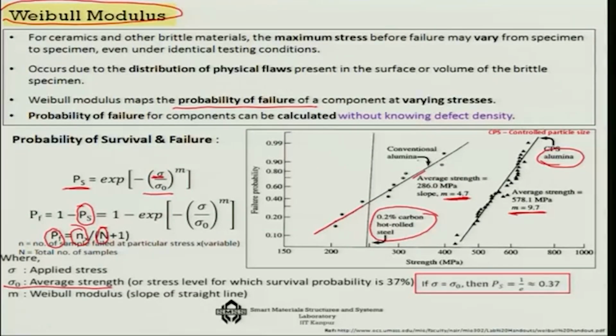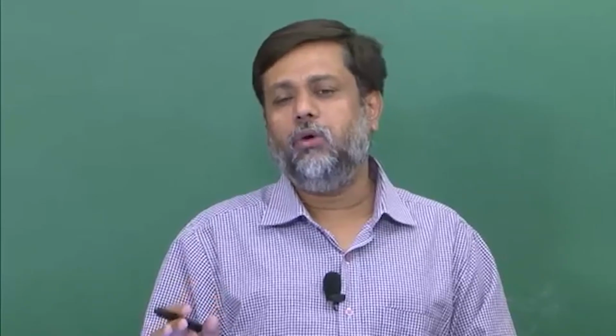So, this tells us that the Weibull modulus is a very important factor, because it gives us an idea of the variation of strength or such mechanical properties in ceramic materials. Secondly, the manufacturing process should be guided in such a manner that we get higher and higher Weibull modulus, so that ceramics can compete with their metallic counterparts, because nobody would like to design a product where the strength can be anything. The strength can be varying between, suppose, 100 MPa to 1000 MPa. You would not like to design a product like that. So, you would like to design a product with a material which gives a higher value of Weibull modulus.